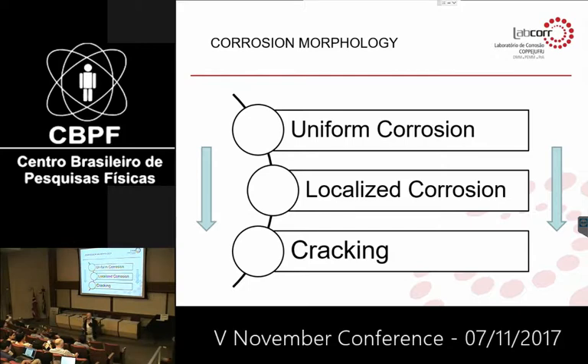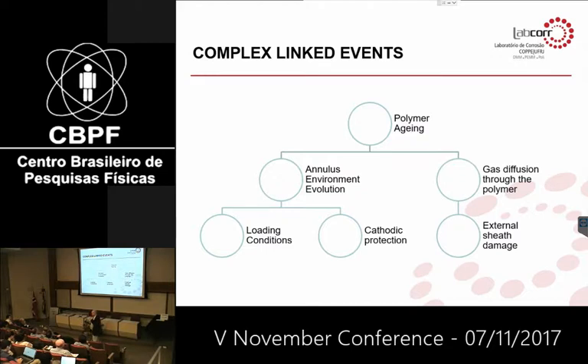A CO2-rich environment is acid, so the corrosion will be followed by hydrogen generation. H2S ingress in the annular environment can drive to hydrogen embrittlement, etc. Another possibility is chloride-induced stress corrosion cracking. It's not an issue in the case of carbon steels; it's related to stainless steels. And alkaline stress corrosion cracking, and different possibilities of cracking in the environment that can affect the steel in the armor wire. So the question is to understand how you can move to critical conditions where these processes can occur.